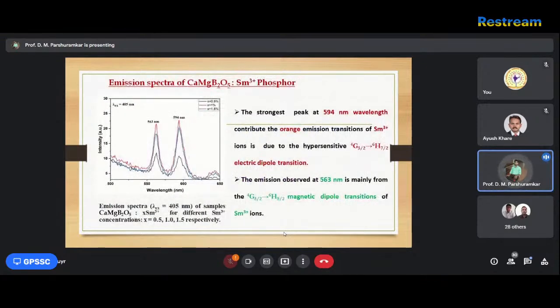Then the other spectrum we got is the emission spectrum of CaMgB2O5 Sm3+ phosphor using the excitation at 405 nanometer, which has the highest peak in the excitation spectrum. Therefore, we chose that excitation to analyze the emission spectrum, and the results are shown in the diagram. The strongest peak at 594 nanometer wavelength is observed, which contributes the orange emission of the Sm3+ ion, due to the hypersensitive 4G5/2 to 6H7/2 electric dipole transition. Here we observe the electric dipole transition at 594 nanometer wavelength, which is in the orange color range.